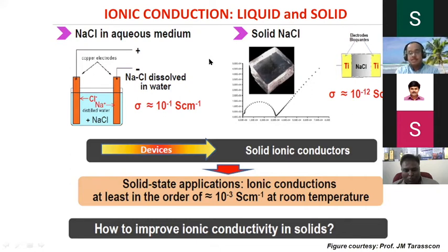Which means that if you want to make a device, the biggest bottleneck is the lithium ionic conductivity of this solid. So if at all you want to realize it, you have to lift the conductivity to at least 10 power minus 3 Siemens per centimeter at room temperature. That's from 10 power minus 12 to 10 power minus 3. Big thing. How do you improve ionic conductivity?